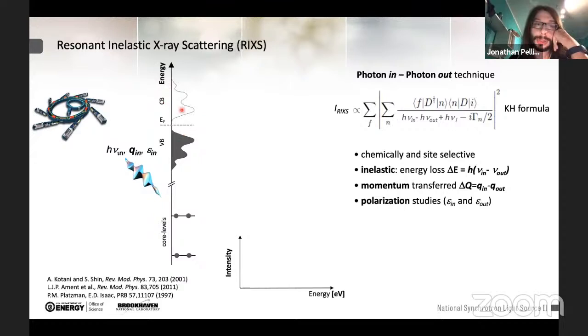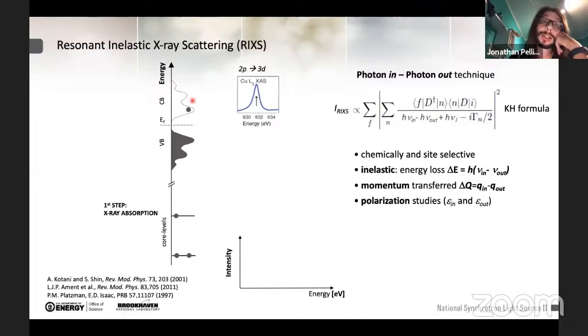When we excite with a resonant photon, we excite one electron from the core level into the conduction band, and we create a highly unstable, short-lived intermediate state, which is also equivalent to what we call X-ray absorption spectroscopy. This intermediate state is unstable because it has a core hole and it has to relax somehow. And what is happening is that a valence band electron can jump into this core level, filling it in with the consequent emission of an outgoing photon with a specific energy, momentum, and polarization.